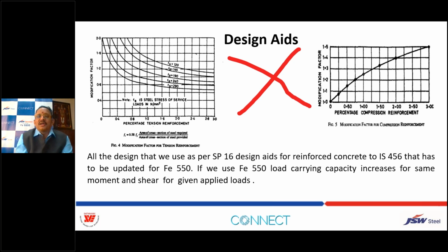And design aids, I have come across, in fact, when I asked my team, what is the disadvantage of using 550? They said we don't have this modification factor for the deflection check in the IS 456 modification factor. So I always say that please don't use the L by D ratio. You calculate the elastic deflection and calculate the long-term deflection, and then use this percentage for modification factor and try to give adequate provision for this modification factor instead of bothering about this modification factor for this.